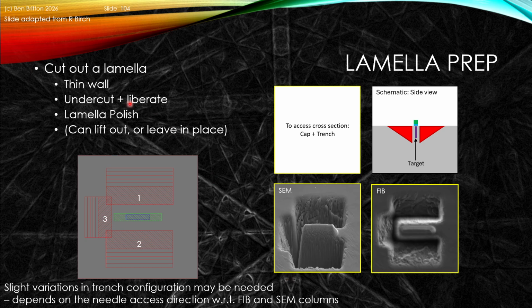So to perform a lamella preparation route, traditionally what we will do is we'll have a target region, we will cap the top surface of this object, and then we perform side trenches where we'll gradually polish in to leave us the target and some thickness either side. We've gone down the trenches on either side, and this is looking at in the SEM, and we'll do a series of staircase cuts as presented here, and these are the E-beam and I-beam caps that were prepared on the top of the surface.